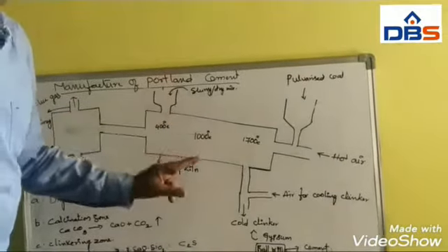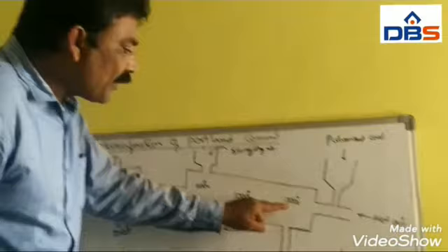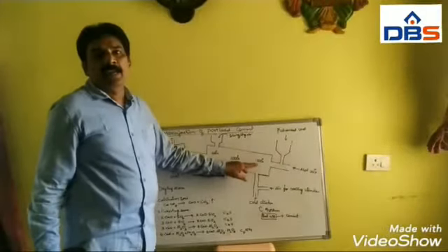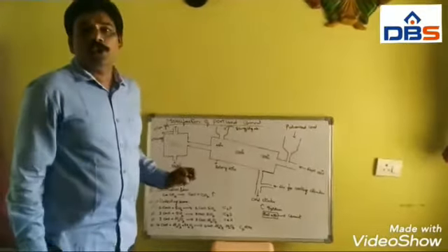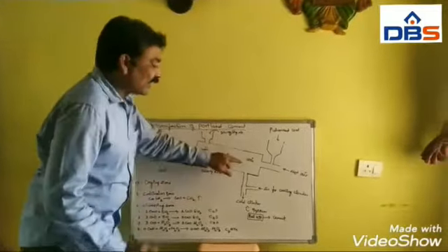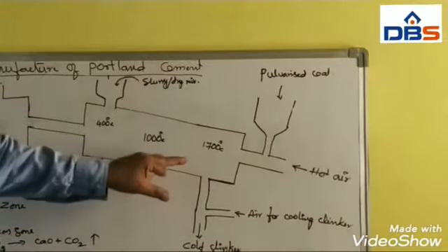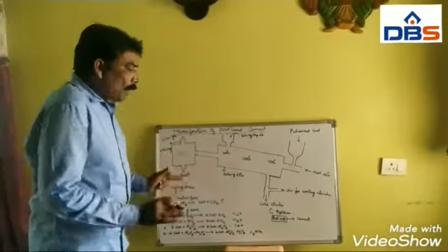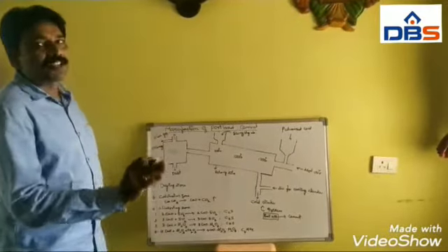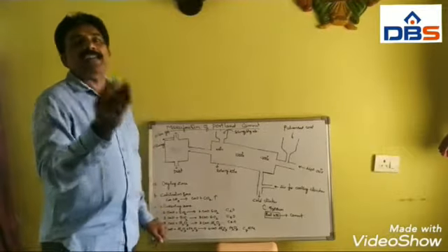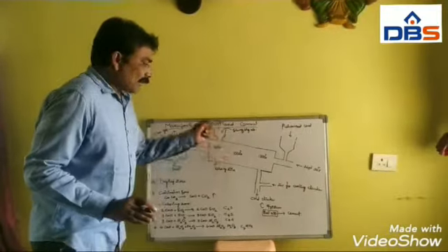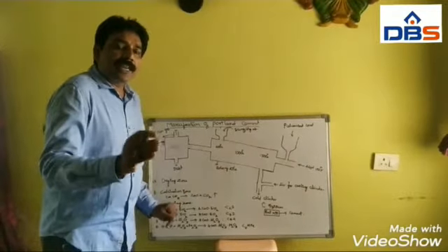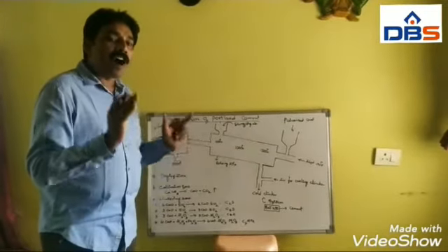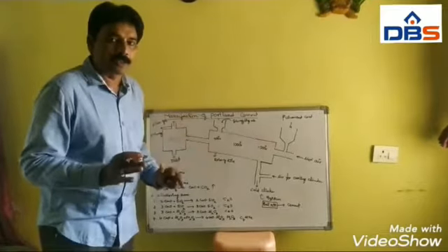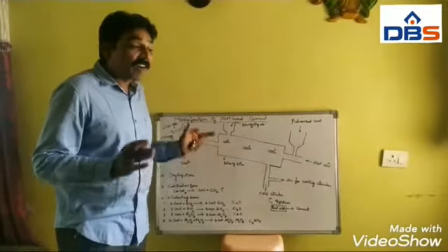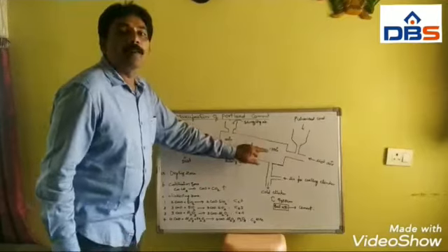The bottom of the rotary kiln is maintained between 1500 and 1700 degrees centigrade. The lime and clay react at the bottom of the rotary kiln to form calcium aluminates and calcium silicates. These calcium silicates and calcium aluminates form hot, greyish stones, just like clinkers. Hot clinkers are produced at the bottom of the rotary kiln.